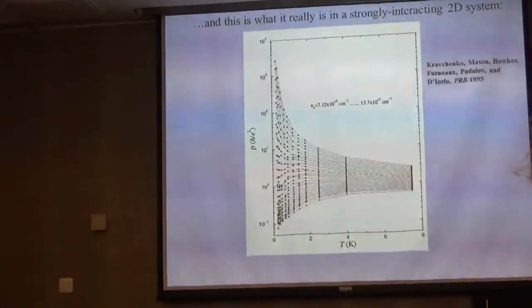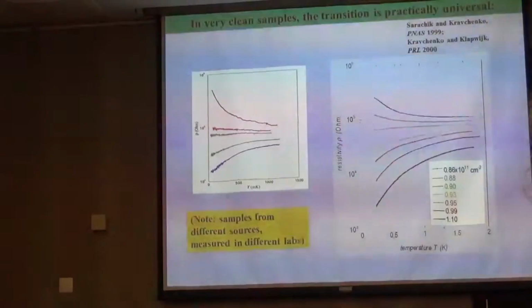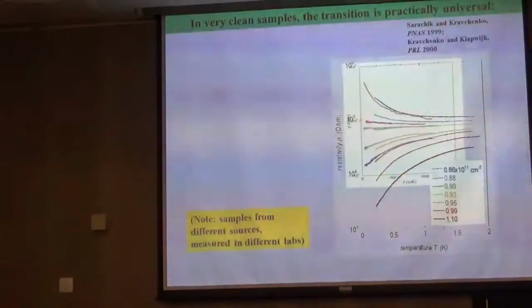Moreover, that was not our first publication on the subject, but it's probably the better one. The first paper was published in 1994. That's a better picture. The samples are brought from Russia. And here is a sample made by Tim Klapwijk in Delft. That's a Russian sample, that's a Dutch sample. If you put them one on top of each other, you see the behavior is practically identical. The samples were measured in different labs in different countries, and were manufactured differently, but the behavior is very, very universal.